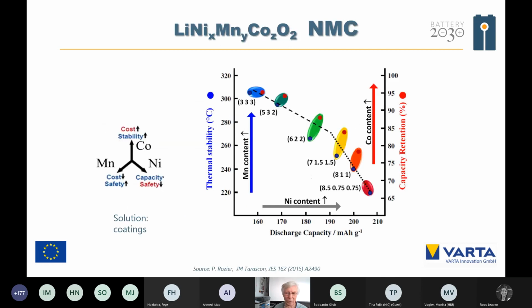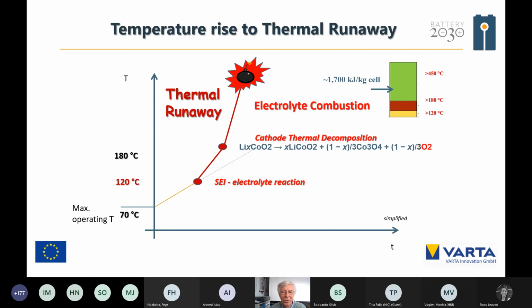And you know the development of the NMC. We are coming from the 3.3.3 or 1.1.1 to the 8.1.1. It's a higher capacity. It's very good. But the thermal stability is decreased as well. So we have higher capacity but lower stability. And what the developers are doing, they are working with layers on the nickel material. So, if the temperature is increasing, we are coming to the electrolyte combustion with a very high enthalpy value.